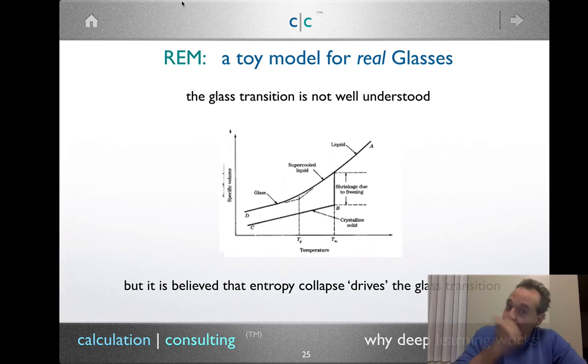But what I mean by a glass is a supercooled liquid. Imagine taking the liquid in this glass of tea and cooling it, but cooling it very, very quickly. If we were to cool it very, very quickly, its specific volume, the volume that it has, would not shrink. In most systems, unfortunately other than water, which behaves opposite, if you have a liquid and you cool it, it will shrink. It will shrink due to freezing. So a metal, for example, as you cool a metal, it shrinks. If you heat a metal, it expands. So there's a temperature at which that occurs. And a liquid will become a crystalline solid.